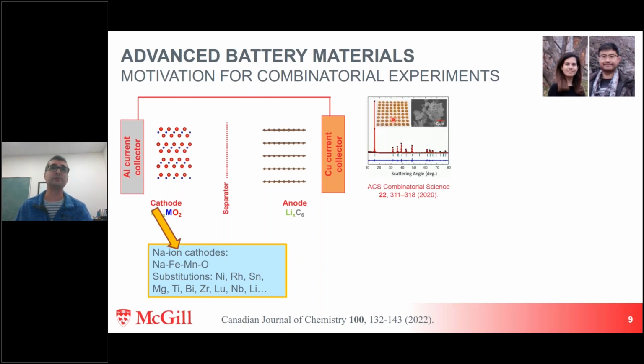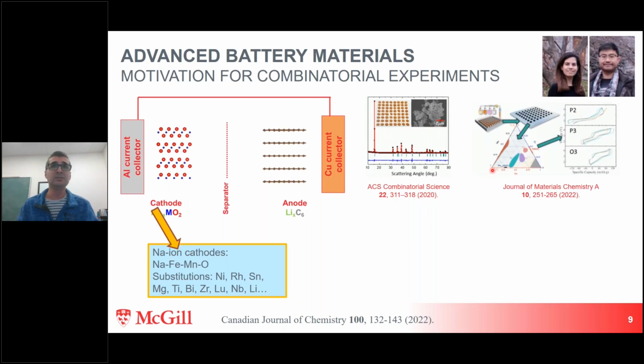So first thing we did was to make sure we were able to make these small samples, and they perform the exact same way as when you make kilograms of the stuff. It's really important that we do this high throughput in a way that scales up. And so that was the first paper. I won't talk too much about this. This worked very well. The performance is very comparable to what you get in large scale. So then we went on and did a ternary diagram, and we found some very interesting materials. I'll talk about this in more detail.